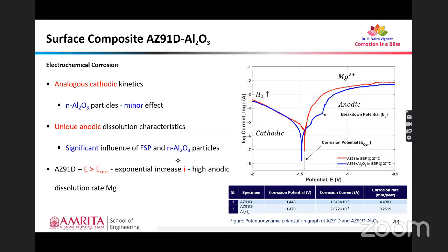So from this we can observe that the corrosion potential of the base material was more noble than that of the fabricated surface composite. But coming towards the corrosion rate, the specimen with the surface composite had a very low corrosion rate than that of the base material. So we have to analyze this in detail. So we have gone for AFM analysis too.